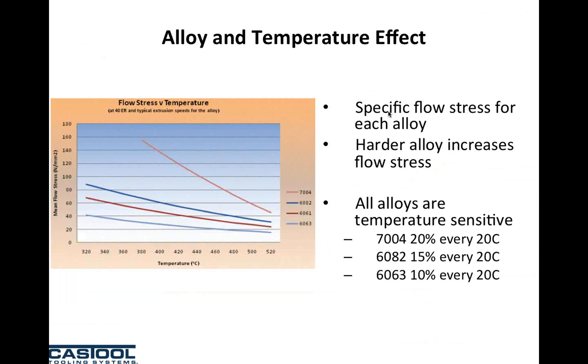But then when we look at the temperature effect, it's exponential. So all alloys are temperature sensitive. You can see 7000 series alloy: every time you drop the temperature by 20 degrees Celsius, the flow stress increases by 20%. And 6063, 20 degrees Celsius by 10%. Compared to what Paul just mentioned, ram speed is relatively insensitive, and temperature is very, very sensitive to flow stress.